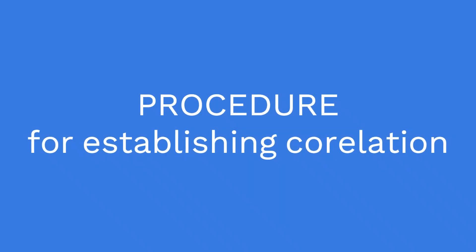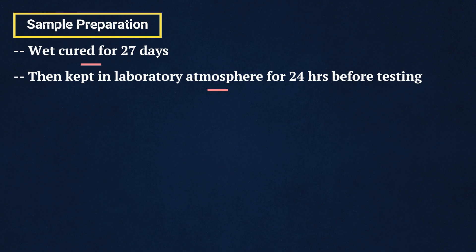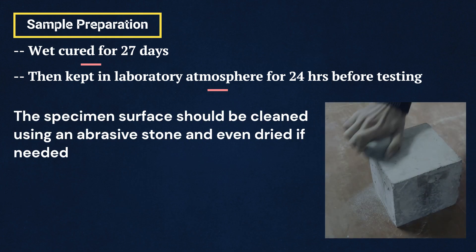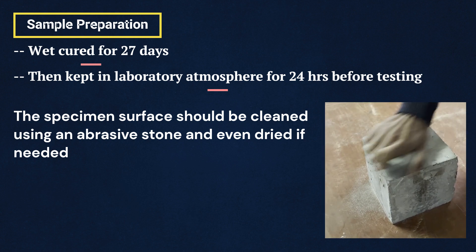Procedure Step 1 Sample Preparation: The cube specimens must be wet cured for 27 days and later kept in laboratory atmosphere for around 24 hours before testing. Clean the surface to be tested by rubbing with an abrasive stone.